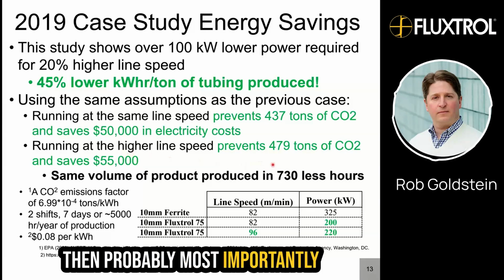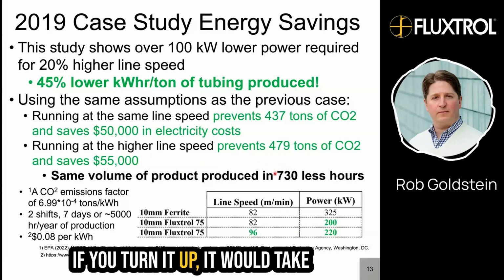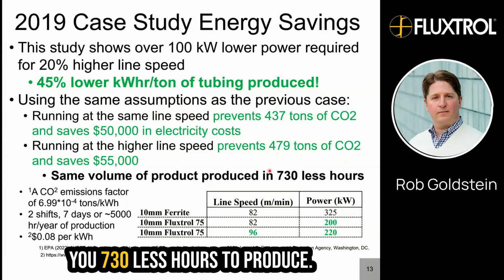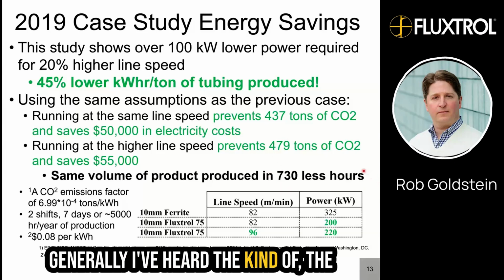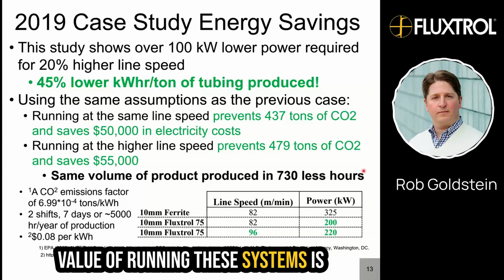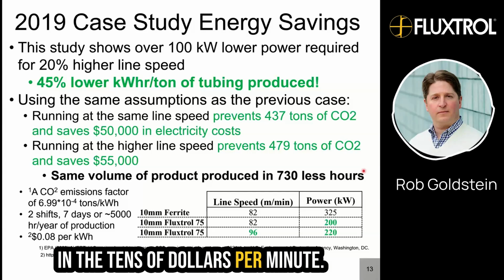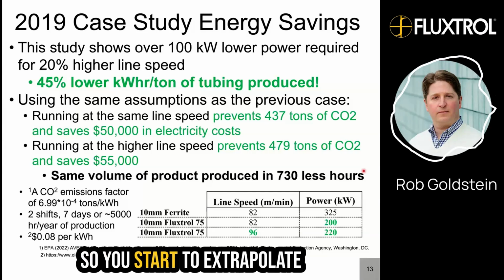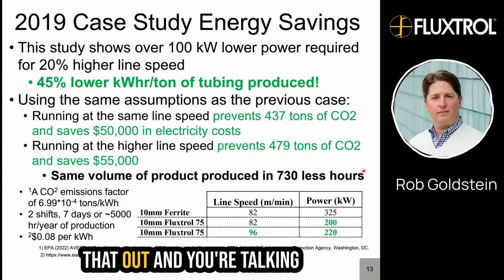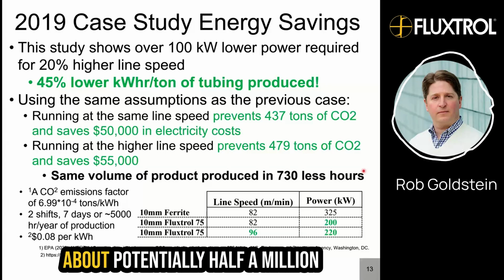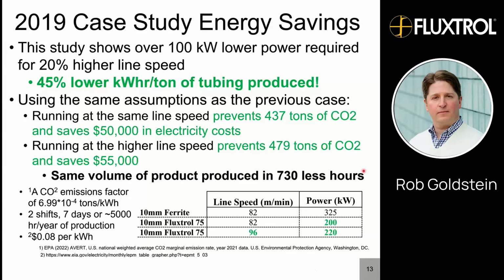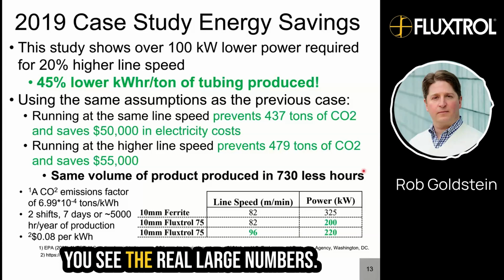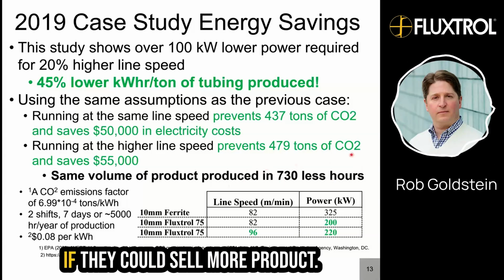Then probably most importantly, if you turn it up, it would take you 730 fewer hours to produce. Generally, I've heard the value of running these systems is in the tens of dollars per minute. So you start to extrapolate that out, and you're talking about potentially $500,000 of extra productivity. So those are where you see the real large numbers, if they could sell more product.